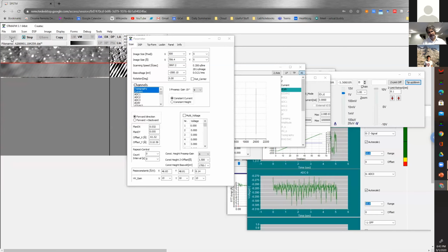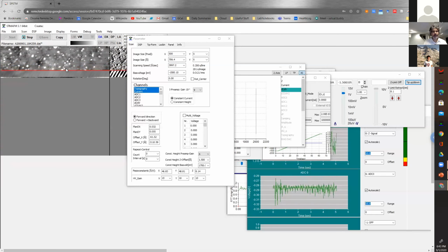So what I did now is zoom out a little bit. This is an 800 angstrom image, so 80 nanometers by 80 nanometers. You can see a variety of these little specks. There are these bright spots here, which we think are actually clusters of gallium. There are these dark spots, which Rebecca is studying, iron.